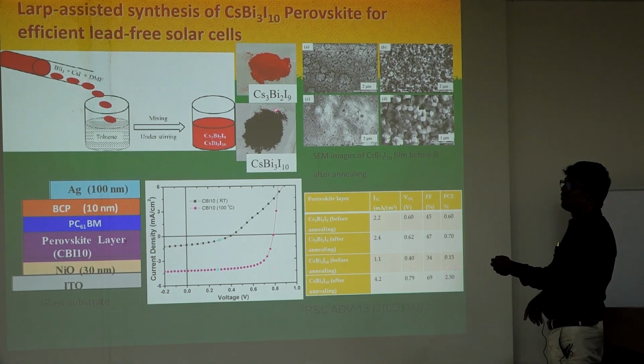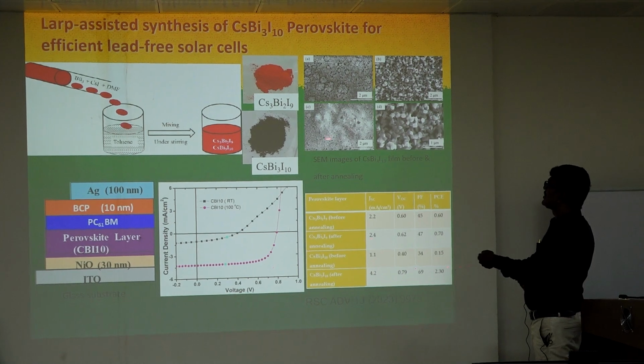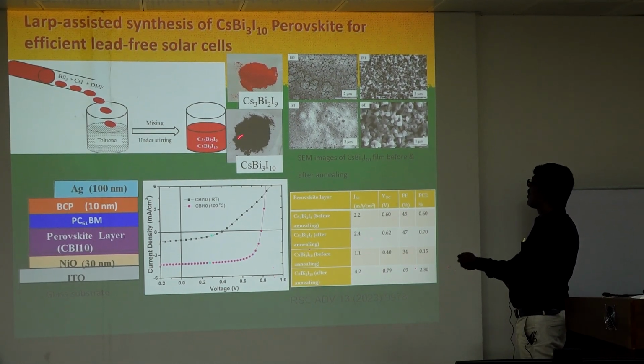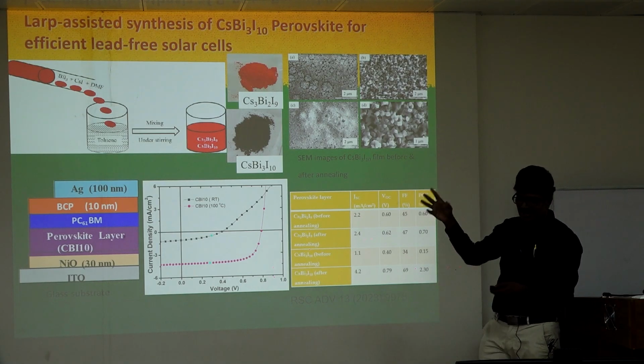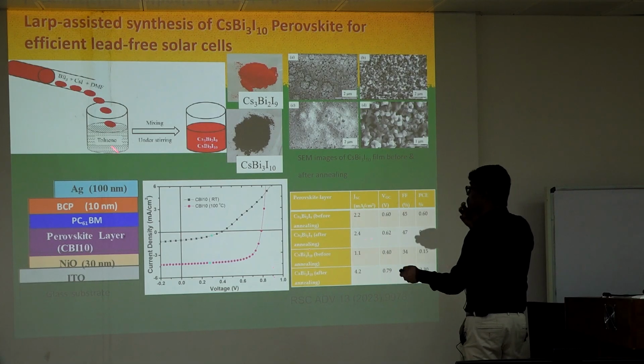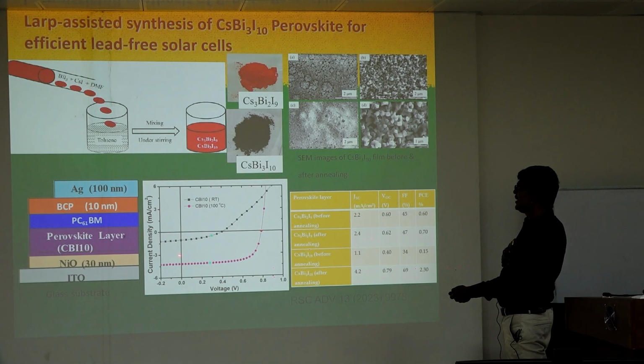In normal condition, without calcination, it becomes orange in color and amorphous, and the images are not good. When you calcinate, only then does it form perovskite. That's very important here. We generally work with the same material, but we don't get any image. Dr. Jagadish uses the material and calcinates it under different conditions, converting the compound to the perovskite form, and once he gets perovskite, he makes a solar cell. He got a very low efficiency initially, we can say 2.3%.